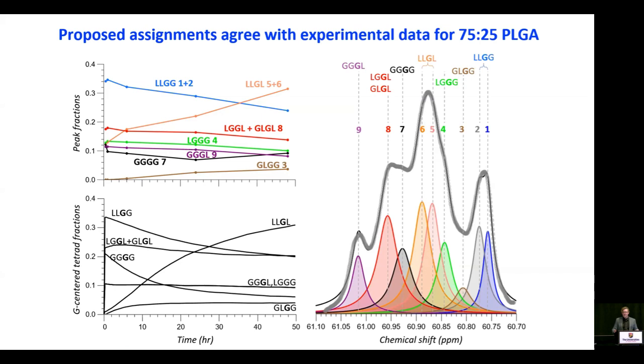So the next test to see if this is right is to change the composition of the polymerization. This was 75-25 lactide glycolide. Now we'll change that to 40-60, and our assignments still hold up. They still survive that change in composition. Okay, so now we have these assignments.